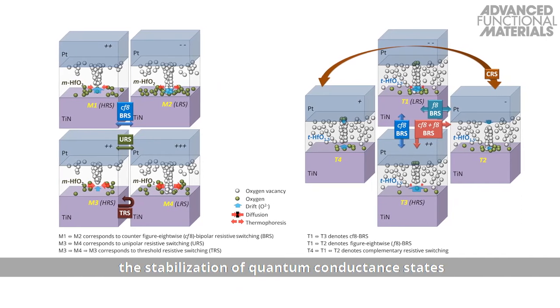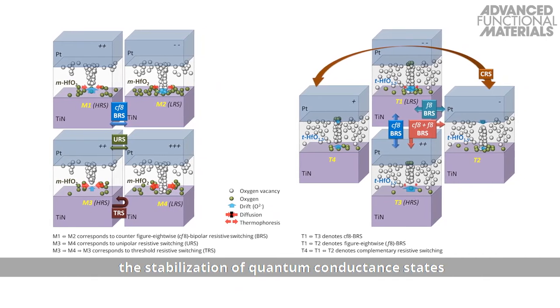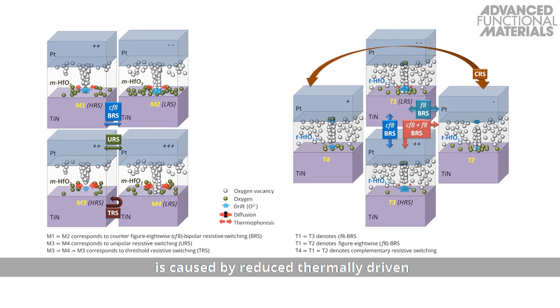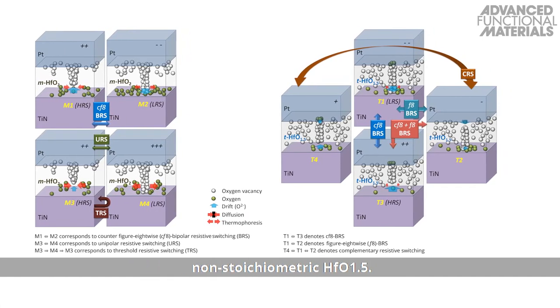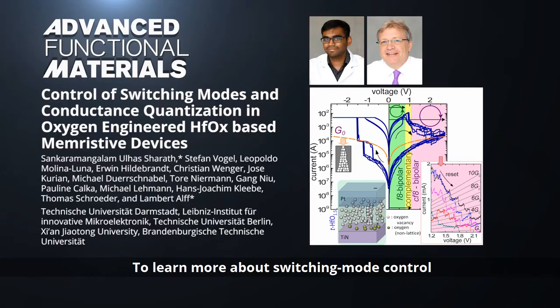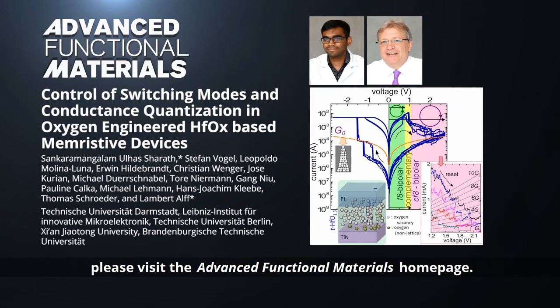According to this model, the stabilization of quantum conductance states is caused by reduced thermally driven ionic or vacancy motion in tetragonal non-stoichiometric hafnium oxide. To learn more about switching mode control of hafnium oxide-based memristive devices, please visit the Advanced Functional Materials homepage.